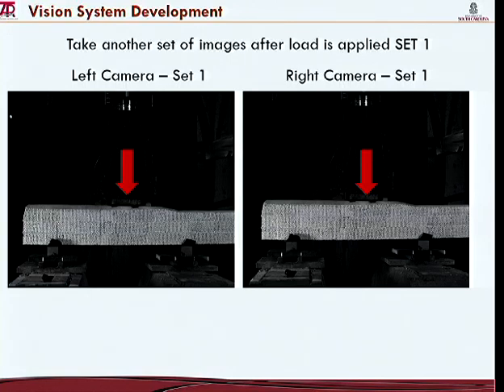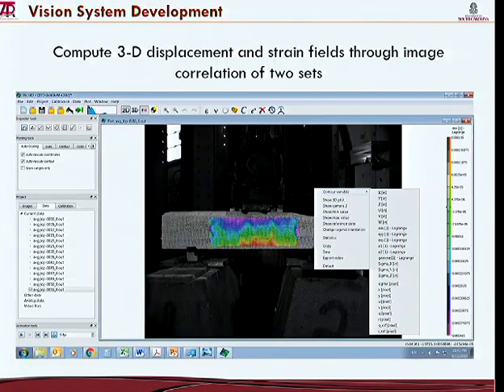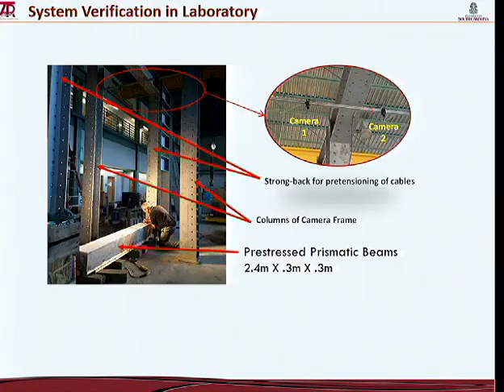So we compute displacements in all 3 directions. Of course, you can post-process them and compute the strain fields. And this has been used extensively, has been validated in the lab. Here is one of the validation tests that I will show you today. This is a prestressed prismatic beam, and the objective here is to measure the strain surface, the strains that develop on the top surface of the beam when the strands are released. These are small strains, so you need an accurate and noise-free system to get the accuracy that it's required.